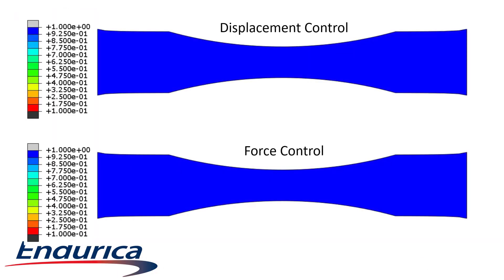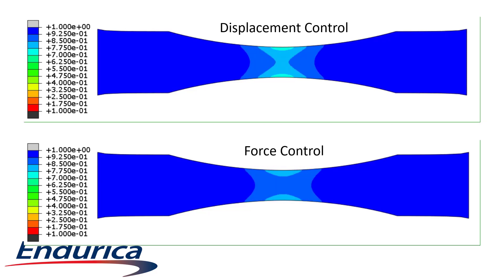Here you see some of the combined results from the workflow time steps. These are contour plots of the stiffness loss ratios for the two loadings. The models start with 100% of their original stiffness. By the end of the simulation, the most damaged elements have a stiffness of only 10% of their original stiffness.